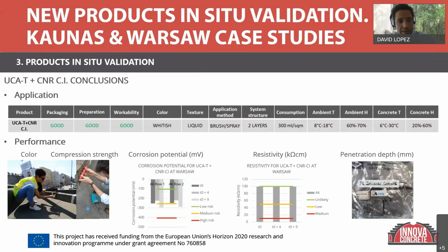And here, just to mention, as Cristiano was mentioning, we measured the corrosion potential and the resistivity. When measuring the corrosion potential after 4 months, we got an improvement of the concrete. But after 9 months, we got a bad result again. No? So now we are checking what can be happening. For that, we are going to use certain samples that we obtained, as you can see here on the right-hand side, and we're testing them in the laboratory to get some clarity on the validation of these results.